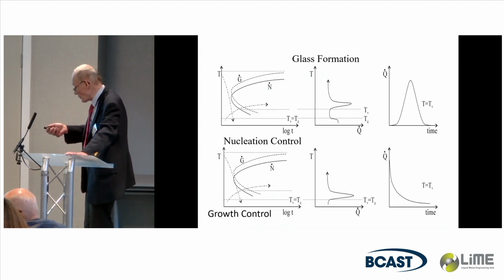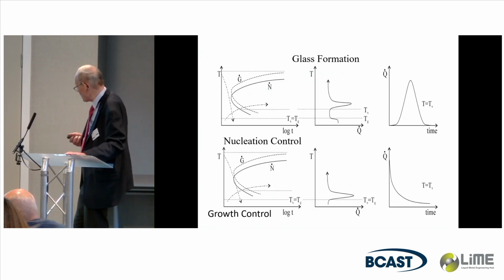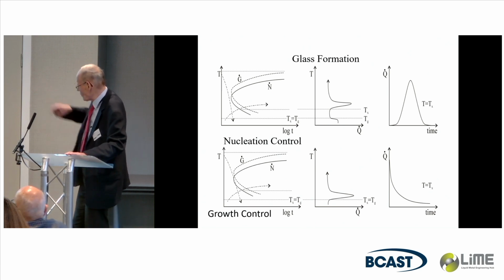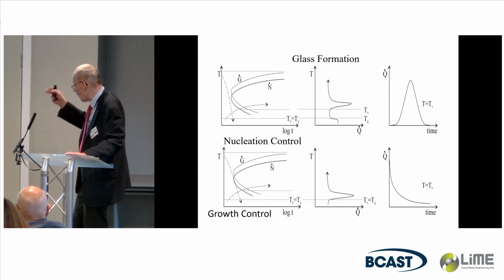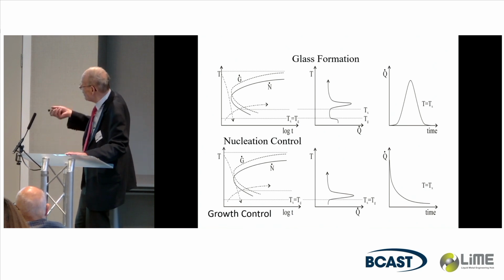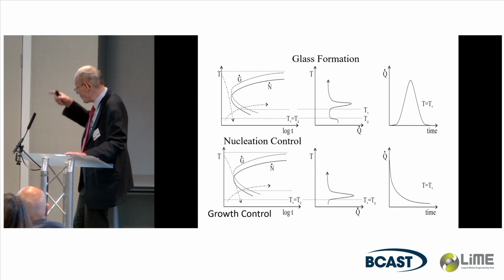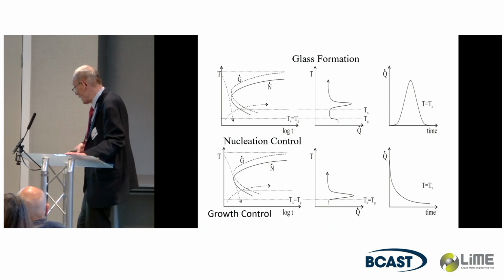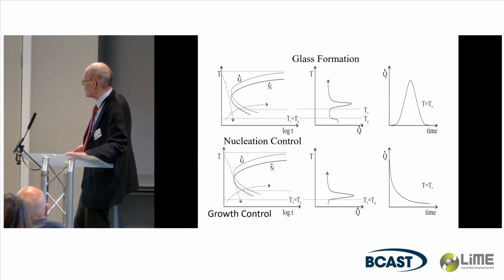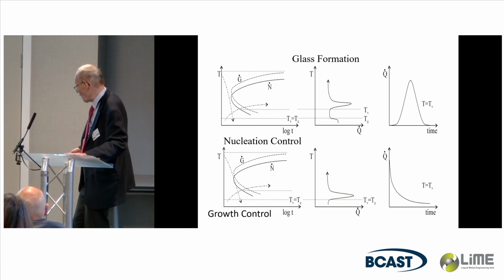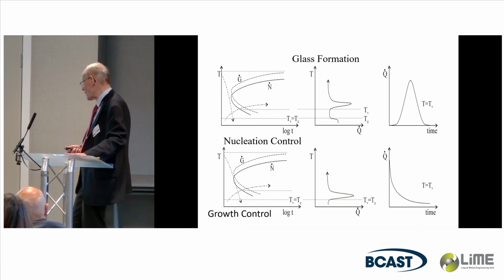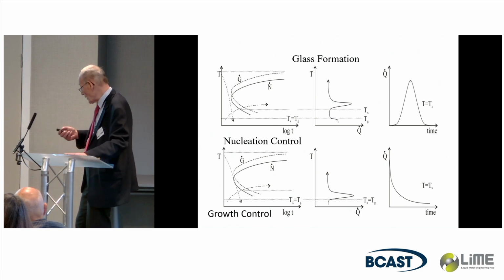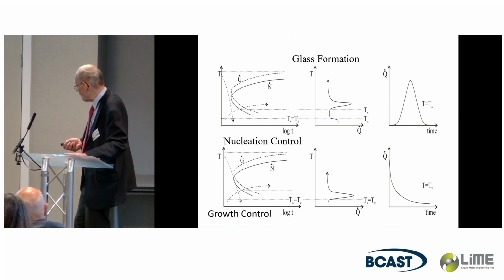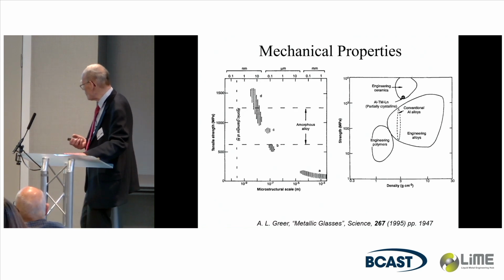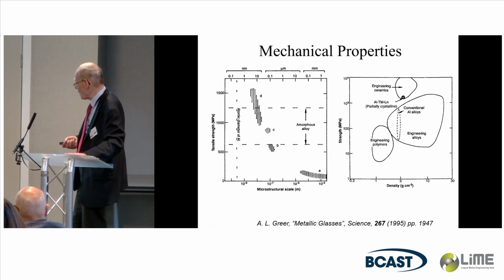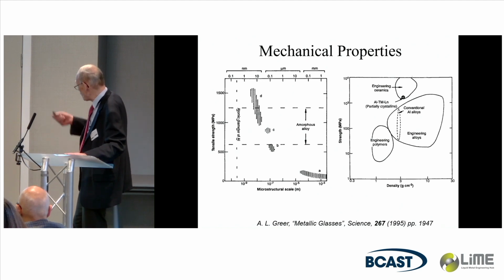All right, so glass formation requires bypassing nucleation and growth. And you can do it either with nucleation control, such as window glass, or with growth control. Here, you recognize that the maximum growth rate is above the nucleation rate in terms of temperature. And so you can quench in a material that has either some quenched-in nuclei or growth-inhibited phases. And that was what we thought aluminum alloys were like. And Lindsay put together this compilation and shows that the